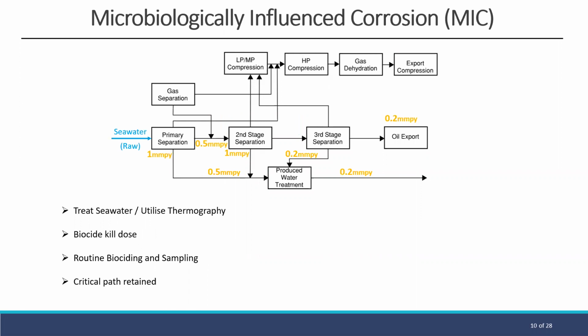Next, we have MIC. So this is prevalent in primary separation, produced water, and the oil export streams. Raw seawater has been used to flush the separators, which is an accelerated area of introducing the bacteria within the system. So we recommend treating this seawater before flushing, or even better, utilizing thermography to detect solids within the separators and only flushing with treated seawater when absolutely necessary. We recommend a biocide kill dose followed up by routine biociding and sampling to ensure effectiveness.